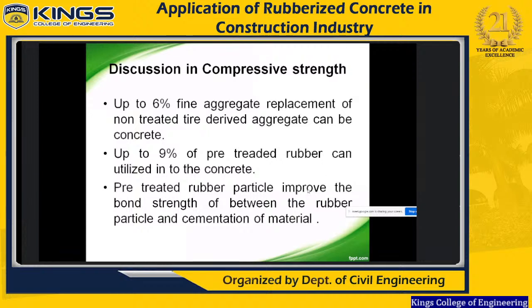But the unit weight is also important. We are aware that if 6% is added, don't think the weight will be less. The unit weight of rubber will be less compared with the coarse and fine aggregate. Somewhere we observed in other graphs the optimum strength of cubes with optimum usage of tire derived aggregates. So here 6% of non-treated, same as 9% of treated. For various days, 7, 14 and 28 days, we have taken 28 days as optimum to mention here.